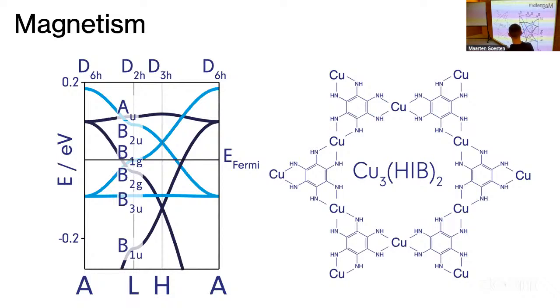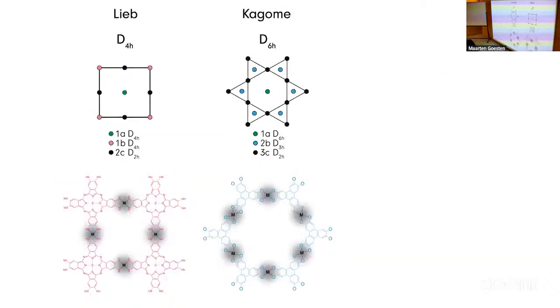What we see here is that this crossing that happens near the Fermi level splits up into chiral crossings. Chiral means that, let's say, light blue is spin up and dark blue is spin down. So this crossing here is spin up, spin down, and this crossing here is spin down, spin up. They are related to each other. So these kinds of MOFs appear to be semi-metals. There's still a lot of theory work to be done.